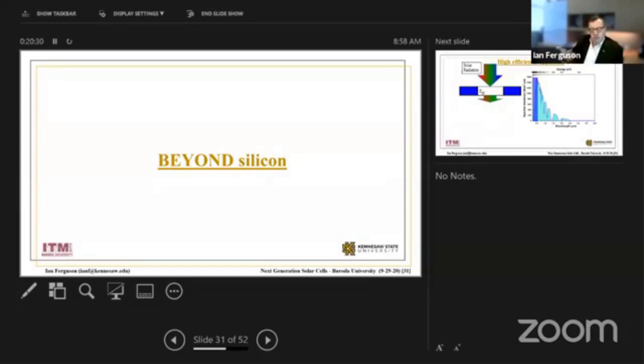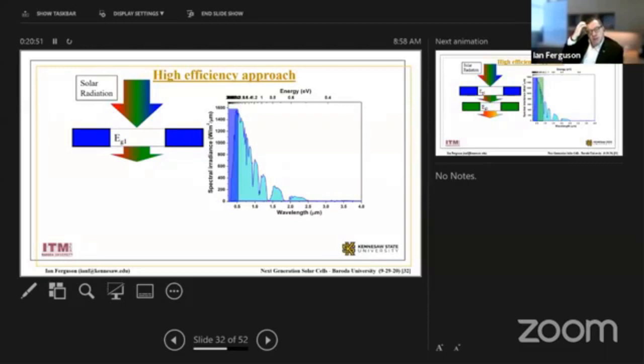So to get significant absorption in it, you need 100 or 200 microns of material, and when you go to direct bandgap materials, you only need about one thousandth of that thickness of material due to the fact that it more efficiently absorbs light.